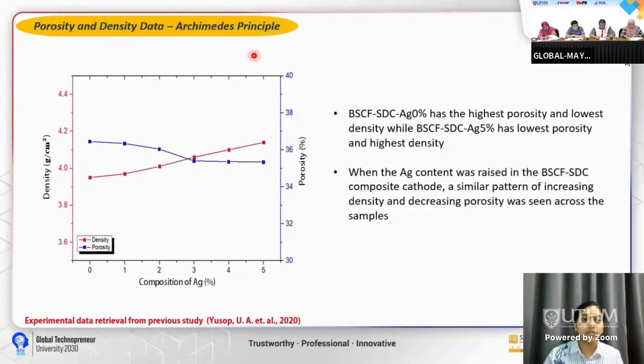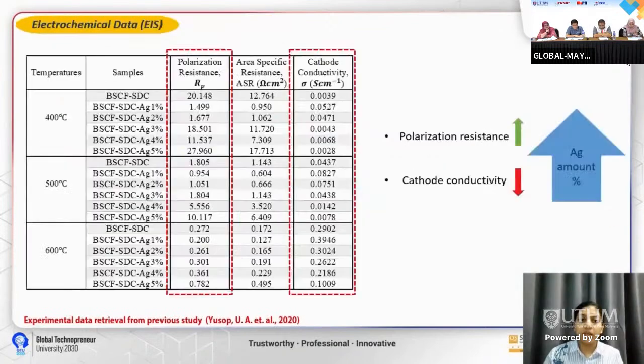The third experimental data used will be the porosity and density data, which were conducted through the Archimedes principle. And from this data, we can say that BSCF-SDC Ag 0% has the highest porosity, while BSCF-SDC Ag 5% has the lowest porosity and the highest density as well. So from this, we can state that when the Ag content was increased in the composite cathode, a similar pattern of increasing density and decreasing porosity was seen across all the samples. And the fourth data, which will be the important one, will be the electrochemical data, which was gathered through EIS equipment.